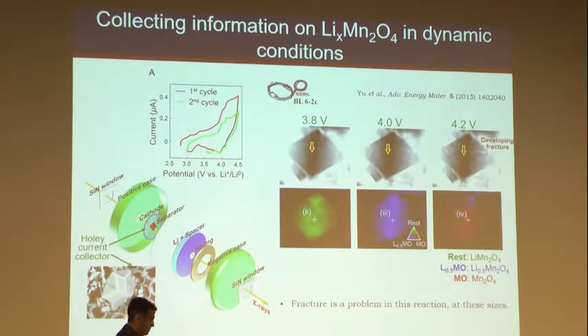So that's what we set out to do. We're not the only ones that did this. There's a number of papers on similar measurements. Our idea was to try to maximize signal. And so what we did is that we put isolated particles with a very well-defined shape, because then by just looking at them, we knew exactly their crystallographic orientation. This is basic mineralogy. And so very defined shape, right size, so that we could get multiple data points within the same particle. And then we mounted them on a copper TEM grid, and copper is a conductor, so that's your current collector, and did the reaction on the copper TEM grid as opposed to building an architecture with carbon and PVDF, which are light, but they still contribute to some absorption.